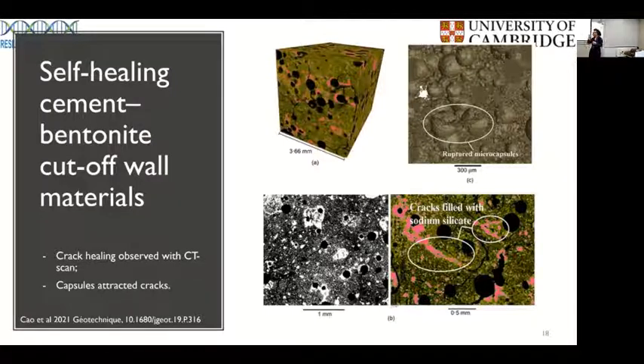So Beni had some small samples of cement bentonite that he cracked and incubated for 28 days in a high humidity environment. And then he observed that same sample again under the CT scan. What he observed was some ruptured microcapsules, but also crack filling of some of these capsules with the healing products associated with sodium silicate.